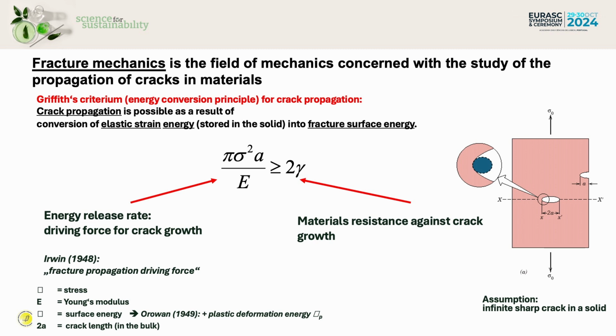That means we have to live with failures. We know it from aircrafts, but it's also in single crystalline microchips. Also there we have to live with failures. And if you see this explanation, then you see on the left-hand side the energy release rate, which depends on the crack dimensions, on the strain in the material, and the Young's modulus. And on the right-hand side, you have the surface energy, which is the material's resistance against crack growth.